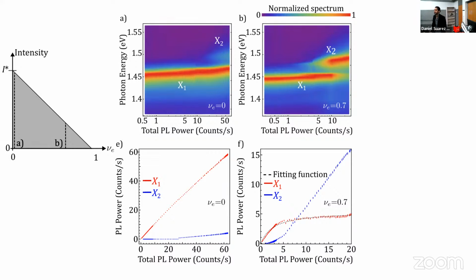A couple of questions about the setup. For instance, you're trying to stay in the Mott regime where U over T is large. But you go to this greatly expanded Moiré lattice, which I would tend to think would reduce U over T by making the particles on average much further apart within each planar orbital. So I was curious about what was going on there, and if you really needed access to the bilayer exciton, and why was that? Why not use an exciton within a single layer for this?